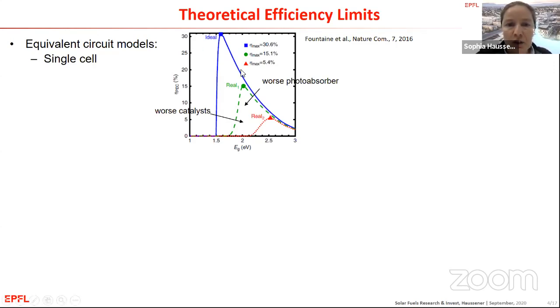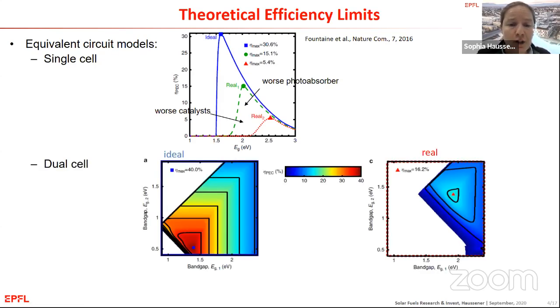So instead of 30, we would have maybe around 15, and you would also require different types of material to satisfy such a device. And you can even further push for higher efficiency by not using only 1 photoabsorber, but 2. Where you can see, if I have now 2 photoabsorbers with 2 different band gaps, you put them nicely in tandem, match their current, and you have effectively the possibility for a 40% efficiency device. And if you go a bit more realistic, it still seems that 16% is not away from anything achievable.